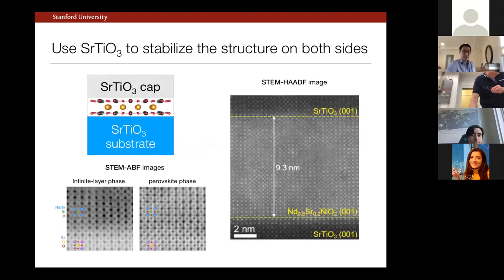So the final step to get to something reasonably stable in the majority of the type of structure that we look at to this day is to take that idea and just double up. Namely, why don't we take advantage of the things we know as a community in making perovskite heterostructures and grow a strontium titanate cap so that we have this proximity stabilization in both directions, okay? And so indeed, this is what we found. This is earlier work, but you can see here a sample of order 9-10 nanometers thick looks reasonably crystalline and coherent in this infinite layer structure. I should say that, by the way, the previous terrible looking TEMs were not Lena or Barrett's doing, the Cornell collaborators', but from here on out, including this one, this is their work.